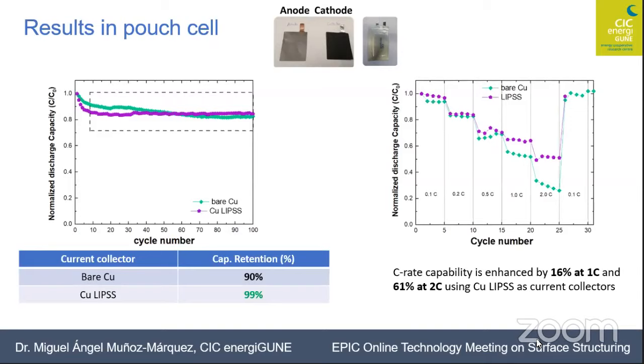What we see here is that the battery has a much better capacity when you structure the current collector. Essentially, you improve by 16% at 1C and 61% at 2C. This point is very important for high power applications, as it allows you to operate the battery very fast. So these two are the main results that we obtained for the batteries. They are very good, high impact results.